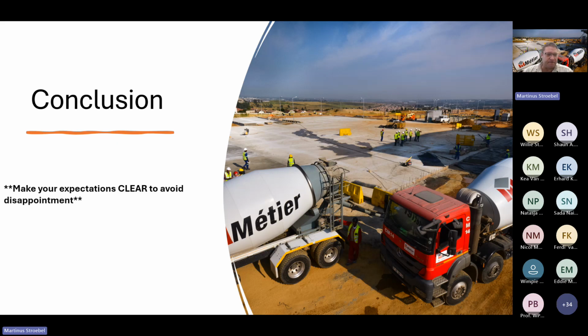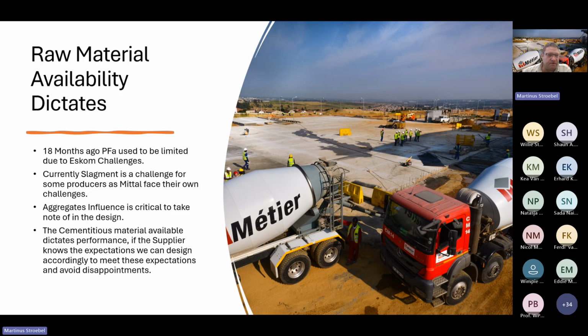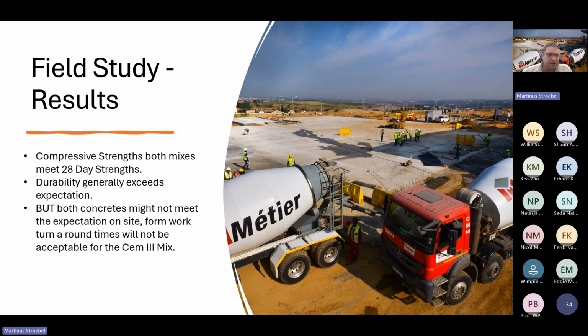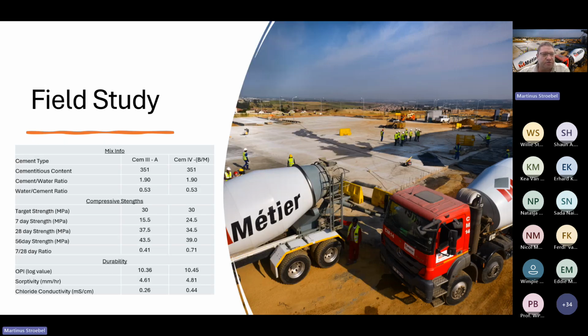I just want to go back, and I think I can show that on the one slide. If you are willing to wait up to 56 days, we can get away with a lower strength concrete to reduce it even further. For instance, we could have used this 30 MPa concrete in a 40 MPa structure, and we would have lowered the carbon content significantly. But in our lives, everything is about speed, and I don't think many customers really want to wait the 56 days before they load a structure. They want to load as quick as possible. So you will have to compromise on time, and time is money. You've got to take that into account.